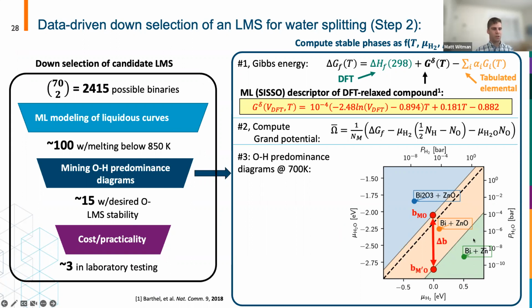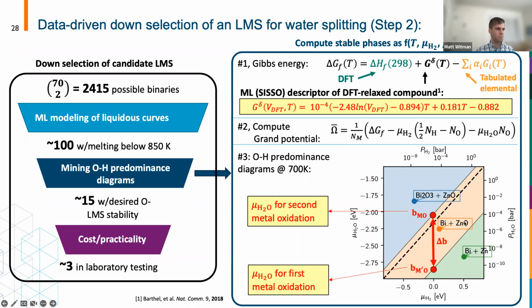But what we're looking at, down here in the bottom right corner, is the fully reduced system. That's our neat liquid metal melt. And as I mentioned, we're looking for preferential oxidation of just one of the metals. So we have these two descriptors: the chemical potential at which the first metal oxidizes, in the zinc bismuth case that's zinc, and then the chemical potential at which the second metal would oxidize. So what we really want are materials that exhibit a range of these, the preferential oxidation of the first metal, and we want large values, or at least non-zero values, of this delta, because we want to be able to oxidize only one of them. So that's what these two descriptors are accounting for.